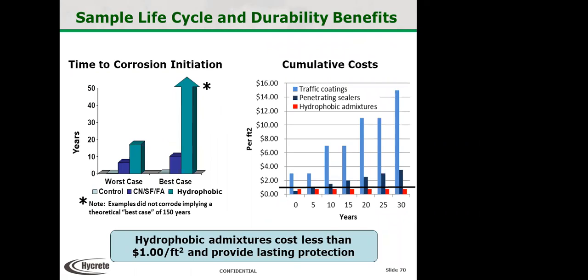Now, this study, which is one of my favorites, on the left, it's a corrosion initiation study. Basically, this was done by the Virginia Transportation Research Council. They tested how it's going to look with a control, regular concrete, how long until corrosion starts, not when the structure is completely corroded, but when corrosion starts to occur visibly. So it's a control. And then they had their high performance mix, which had calcium nitrite, silica fume, and fly ash, and then there's a hydrophobic. That's basically concrete with the hydrophobic in it.